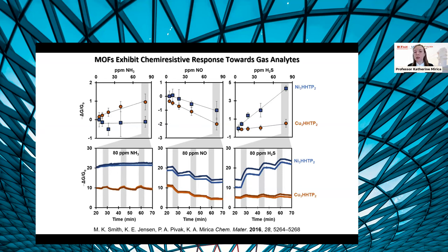Moreover, there's another important feature of the data here that is related to the directionality of response. So we actually see resistance decreasing in response to nitric oxide and resistance increasing in response to hydrogen sulfide and ammonia for the material that responds. That is a typical feature of a p-type semiconductor that becomes more conductive, or decreases its resistance, in response to an oxidizing gas and increases its resistance in response to a reducing gas. So this type of exposure to these gases also tells us something about the semiconductive nature of the materials that we're studying.